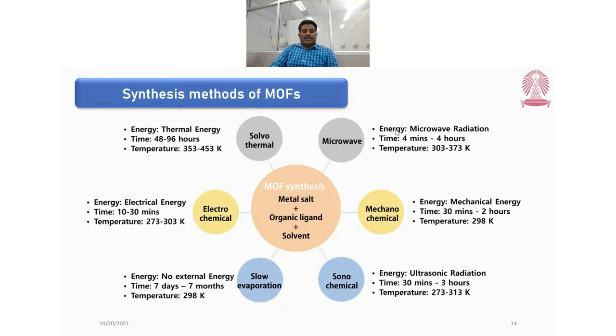Like the sonochemical method, we use ultrasonic radiation. Then the slow evaporation method. This method is a crystal growth method. It will take a long time, 7 days to 7 months. And the electrochemical method, using electrical energy, it can take 10 minutes to 30 minutes.